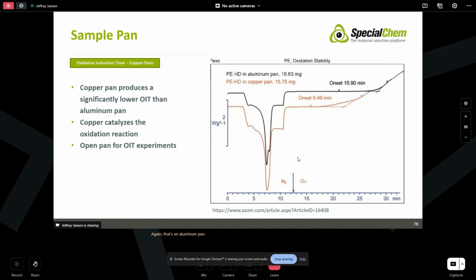Kind of the exception to what you want to do is, certainly for OIT experiments, you need to be exposed to the atmosphere. So you either need to run a pinhole, or more commonly just an open pan to do that. And you get different results whether you run an aluminum pan or a copper pan. With a copper pan, the copper atoms tend to catalyze that oxidation reaction, particularly in polyethylene and polypropylene, where OIT is run a lot. And so usually that's a benefit, to get that OIT to come faster, because oftentimes these experiments can go out to an hour, 2 hours. We don't want them to go necessarily that long. That's a lot of instrument time. So the copper pan helps us to reduce that.